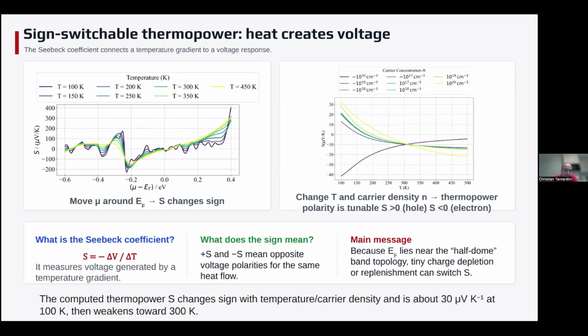So in this way, we see that when we change the temperature, the Seebeck coefficient close to the Fermi level also changes sign, going from positive to negative. Specifically, we see this when we change the carrier concentration. And to be clear, when we have a Seebeck coefficient that is more than 0, we have holes, and when we have a Seebeck coefficient less than 0, we have electrons, in thermoelectrics.